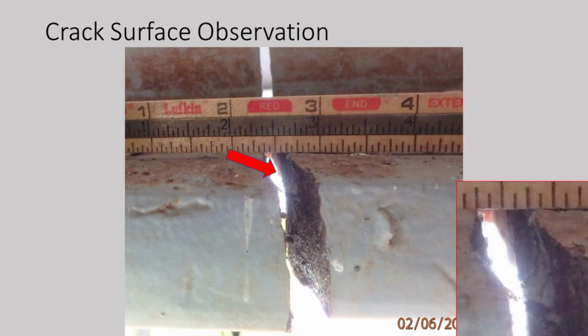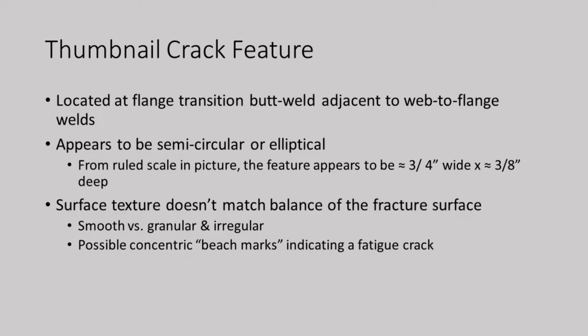Magnify it, and you can see this detail is located in the butt weld, obviously, and it's adjacent to the web-to-flange fillet weld. It appears to be semicircular, called a half-penny crack or elliptical, we don't know, but something like that. And from looking at the ruler, we estimate that it's about 3/4 of an inch wide and maybe 3/8 of an inch deep.